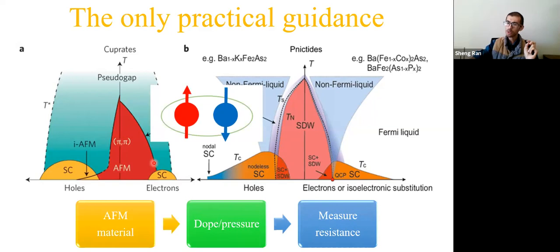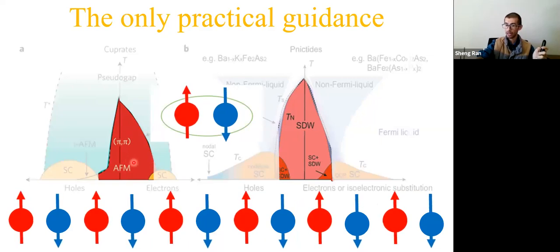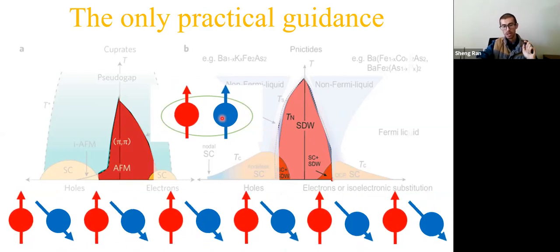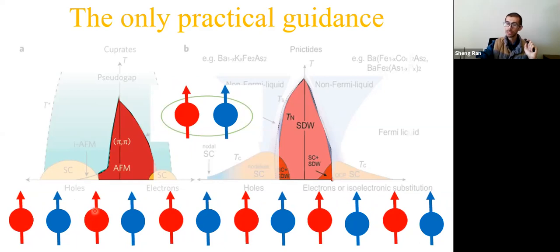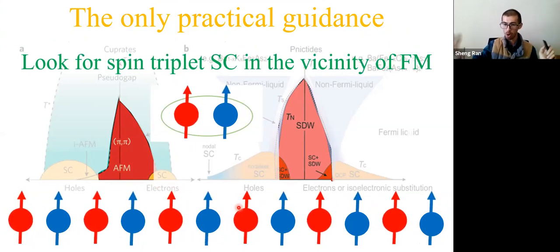And this can be understood in a very simple picture. If we believe the underlying antiferromagnetic fluctuation is important for the Cooper pair, then the antiferromagnet has alternating spin up, spin down. No wonder the fluctuation will only give you this type of pairing. If we're looking for spin triplet pairing, likely we need to look for superconductivity in the vicinity of ferromagnetism. So that's really the starting point of this whole project. That is to look for superconductivity in the vicinity of ferromagnetism.